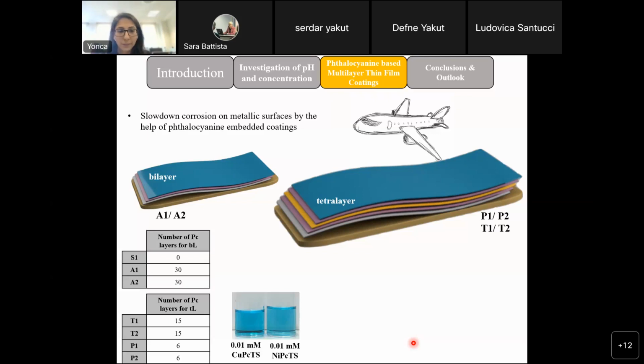So in terms of numbers, I can say that the structures A1 and A2 represent different metalated phthalocyanines. A1 stands for nickel phthalocyanine, A2 stands for the copper phthalocyanine, and they have 30 layers of phthalocyanine. S1 is just blank polyelectrolyte without any phthalocyanine content. And on the tetralayer side, as I said, there is less phthalocyanine, so 15 to 6 layers.